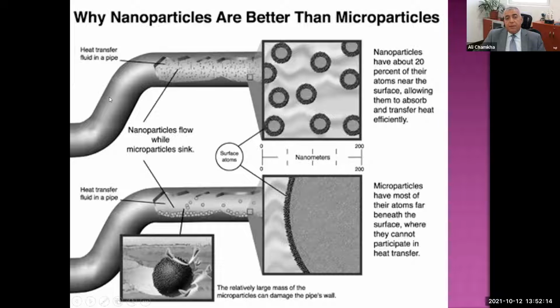If you take a simple pipe system like this, with nanoparticles and microparticles, in principle, nanoparticles remain suspended in the fluid, as you can see here in the picture, while the microparticles settle and tend not to add to the thermal conductivity, and therefore do not enhance heat transfer. They will cause lots of problems in terms of erosion and corrosion of the internal pipe material. In principle, nanoparticles have a high surface area, and much less for microparticles.